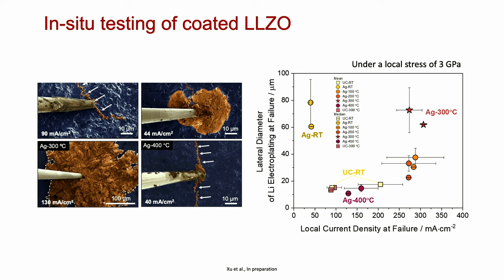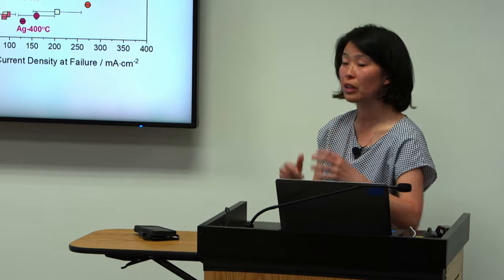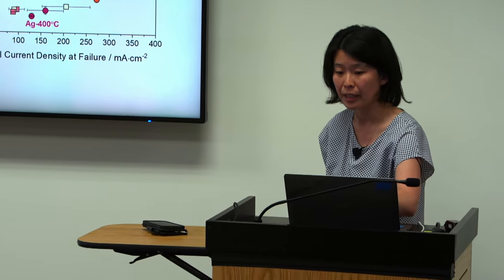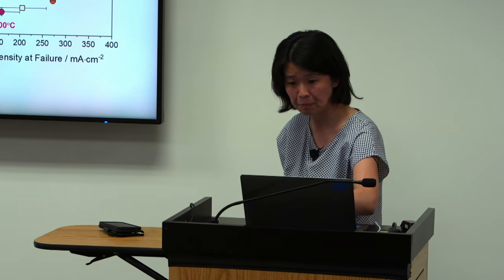So with the silver-coated sample, what we generally saw is that for certain of the conditions, specifically after heating to 300 degrees, we can form much larger lithium plating without the cell being short-circuited. And this is shown by a much higher diameter and also a much higher current density. So this is this performance. And for comparison, the uncoated room temperature sample is down here. So again, this shows that this type of strategy seems to work, at least at the local level, just at the surfaces where the probes are attached. We should probably think deeper about how to scale this.